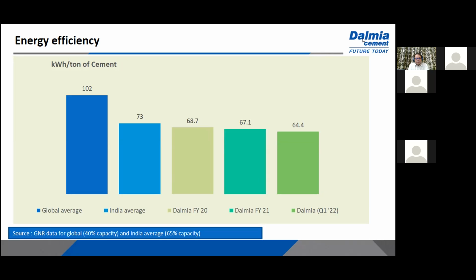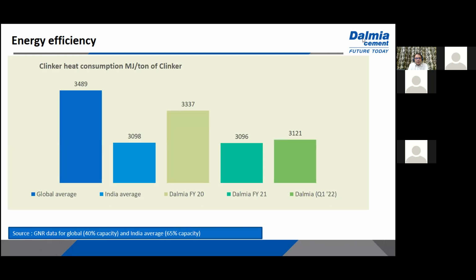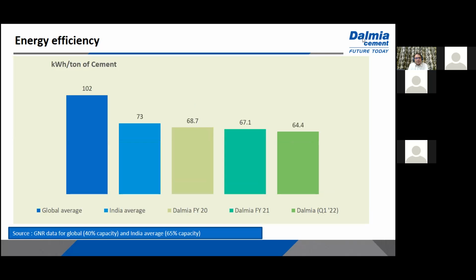The earlier one was the heat consumption of the clinker in megajoule per ton of clinker. So basically this is thermal energy efficiency. And in this slide, you can see the electrical energy efficiency. Again, even in electrical energy efficiency, we are best globally. The Indian average is much lower than the global average in terms of kilowatt hours of energy consumed per ton of cement.